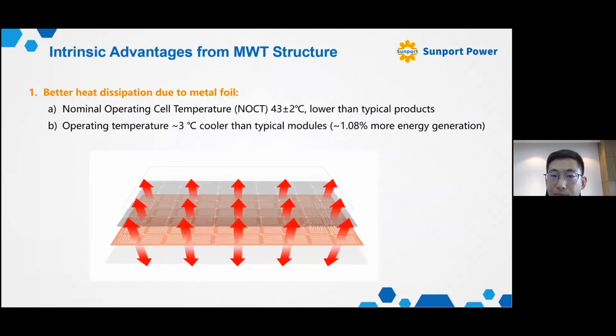And due to the structure design I mentioned, I conclude three intrinsic advantages. So I show them separately here. First, because of the great heat dissipation of the metal foil, the normal operating temperature is 2 degrees lower than the typical module, and the actual operating temperature is roughly 3 degrees cooler, which means roughly 1% more energy will be generated at the same setup.